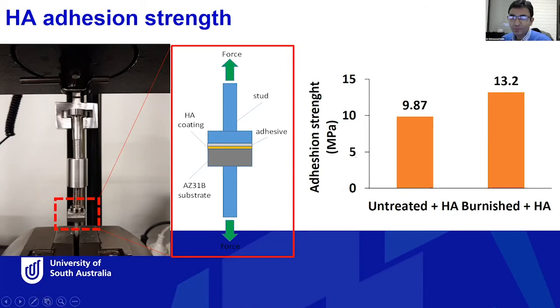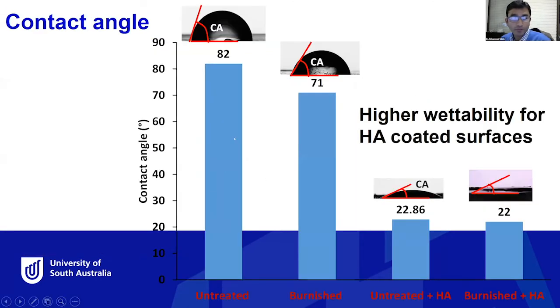Okay, thank you. We can see that for the HA burnished plus HA coated, the adhesion strength is also quite high. You can see it is 13.2 megapascal, and this strength is pretty close to the generally recommended bonding strength for any coating. We have also done some contact angle measurements to indicate the wettability, and we know that a biomaterial and biocoating having much more wettability is going to increase the osseointegration of the implant.